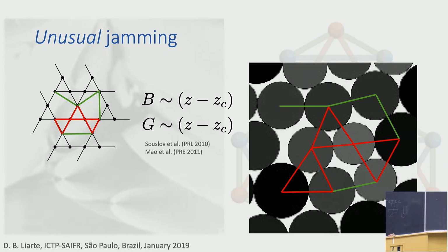So some people might have thought that you could start with an isostatic lattice, a lattice that satisfies this Maxwell constraint argument. And you have, for instance, in the Kagome lattice, 4 contacts, which is actually equal to 2 times the dimension, which is exactly the isostatic limit. So you could dilute some bonds and add some bonds in some random, precisely described way, and study the transition in rigidity from a fluid to a rigid phase. And they find out that they can describe, for instance, a bulk and a shear modulus for a system like this, and they have done it for other lattices as well.